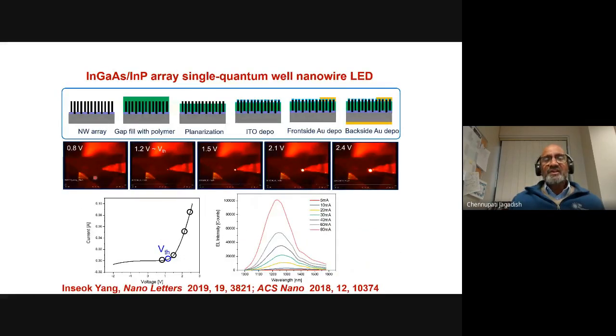Before finishing, In-Suk, instead of using single nanowire LEDs, really tried to make array LEDs, and you can see these nanowires which are grown, and then the challenge is how to make contacts. You can fill this with a polymer material, selectively etch the polymer material with plasma etching, and put some indium tin oxide, and put some metal contact at the top and the bottom. So inject the current and then look at the light coming out of these.